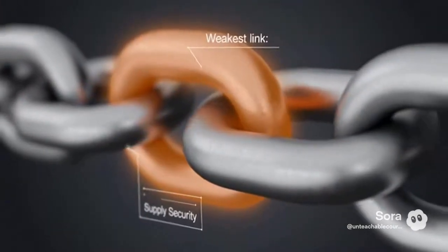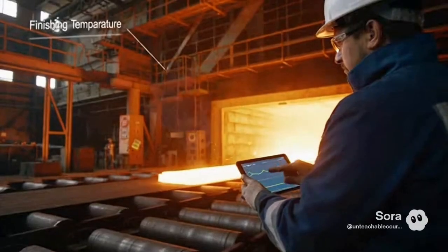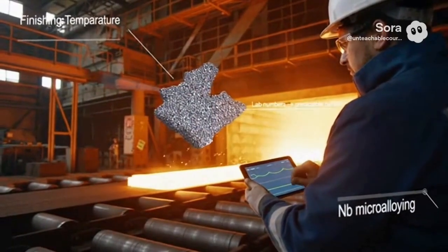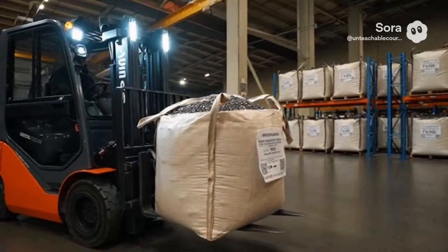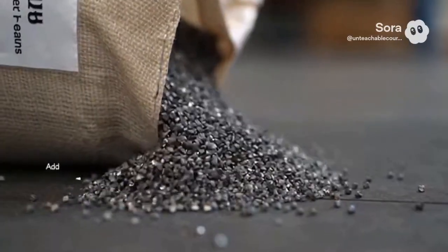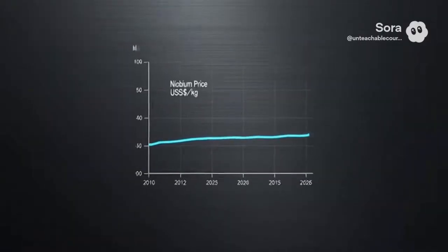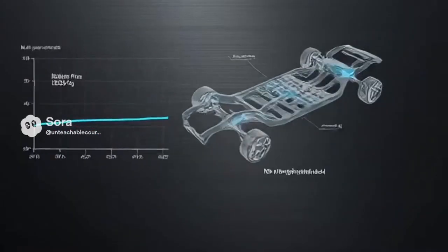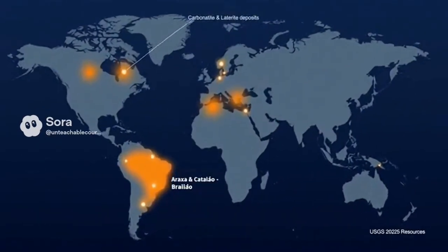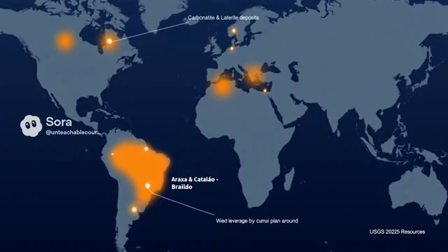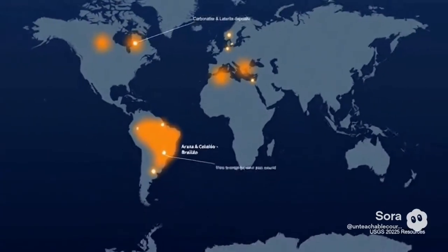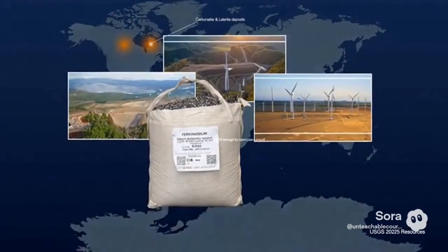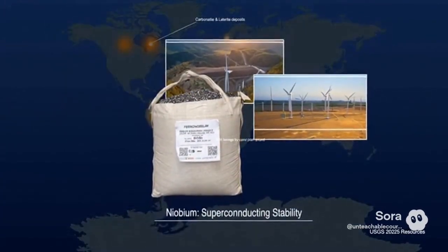Heat treat strategies that de-emphasize microalloying can sometimes skate around the need altogether. But these are not universal substitutions. They are case-by-case rewrites of rolling schedules, die compensation, and weld procedures. The inertia of competence is a moat. A mill that knows niobium's thermomechanical window by heart and a field crew that trusts the heat-affected zone behavior are not in a hurry to rewrite their muscle memory in exchange for a theoretical cost advantage.